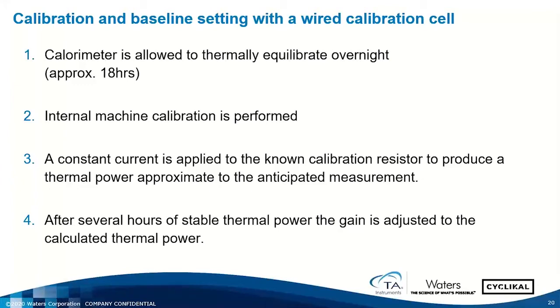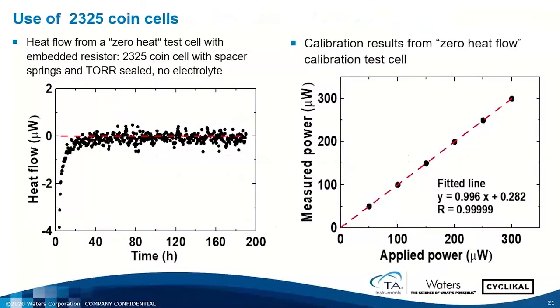All right, when we do that type of procedure, these are the type of results you can expect. And this is from 2325 coin cells. On the left here is a plot of the thermal power versus the time at open circuit. It's just the calibration cell. And you can see the calorimeter can provide very stable thermal power, well less than a microwatt, for approximately 180 hours. And on the right here is a plot of the measured thermal power versus the applied thermal power coming from the calibration resistor.